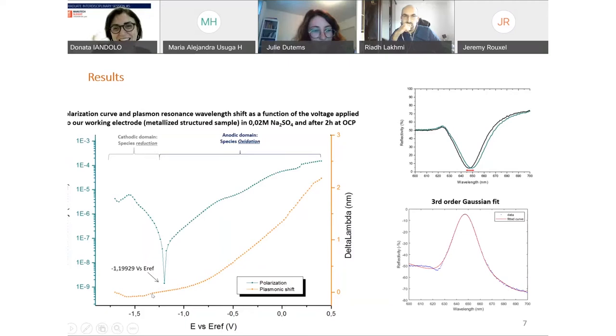The thing is, when you put your sample into the electrolyte, you wait for a few hours for the potential to reach a kind of thermodynamic equilibrium. And then you start to apply the different potentials. The potential may have an influence, which is why we don't really have the same value here and here. It may induce other changes. So that is the reason why we need to do electrochemical impedance spectroscopy, just for example at this potential, to know what's really happening at this potential. Thank you very much for the explanation.